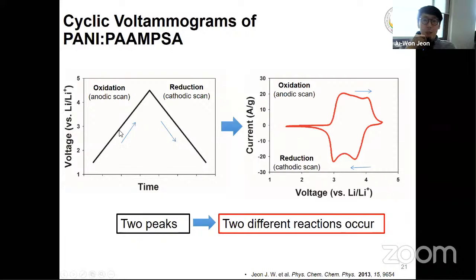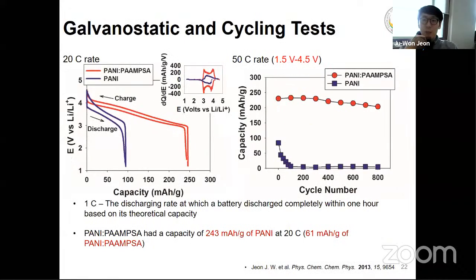So we linearly increase the voltage and linearly decrease the voltage and observe the current response at each voltage. When you increase the voltage, there should be the oxidation reaction, which is called the anodic scan. And if you decrease the voltage, there should be the reduction reaction, which corresponds to the cathodic scan. So we observe two peaks from 1.5 to 4.5 volt for the PAAMPSA, which means two different reactions are taking place in this potential range.